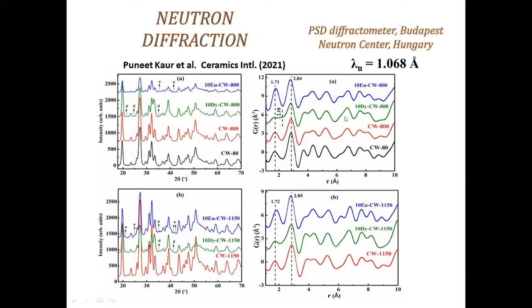These are the pair correlation functions which are calculated from the neutron diffraction patterns. You see the first peak around 1.71 angstrom. These are the W-oxygen bonds, and a second very strong peak around 2.84 angstrom. And these are the oxygen correlations which were missing in the X-ray diffraction studies.